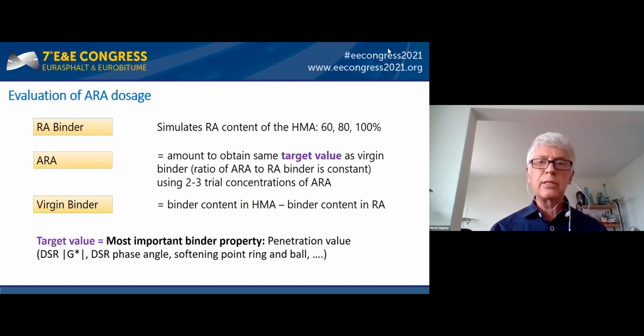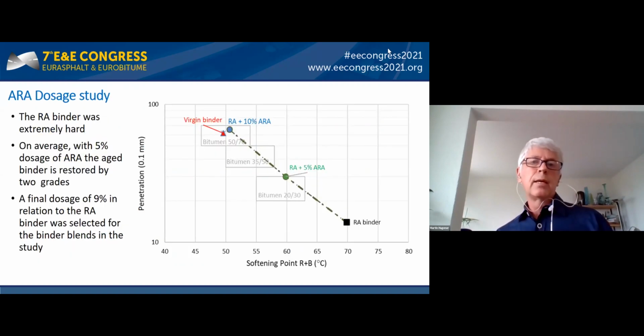So by that, the ratio of the ARA and the reclaimed asphalt binder is constant, so it doesn't matter how much virgin binder we are adding. The target value we choose is quite important, because not every method gives the same ARA dosage. We did choose the penetration value because it's commonly used, but other methods are also possible, like softening point ring and ball, or G star, that's also an option.